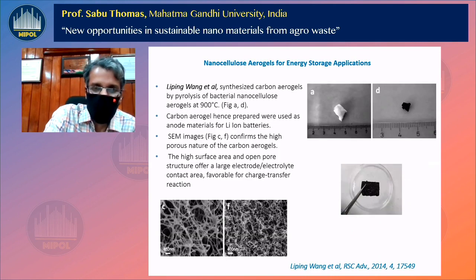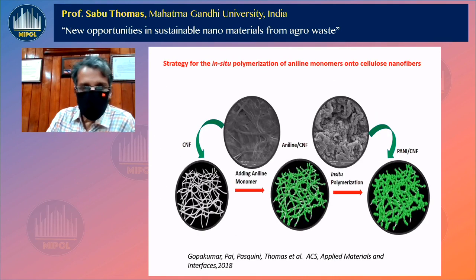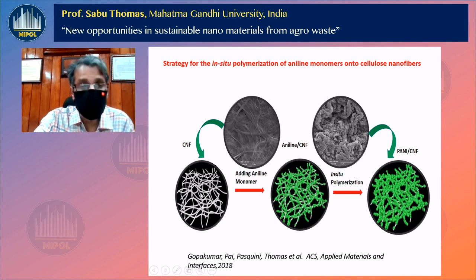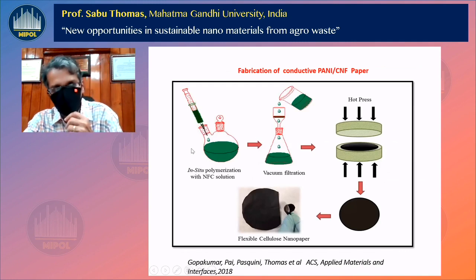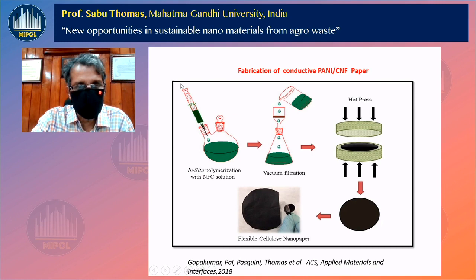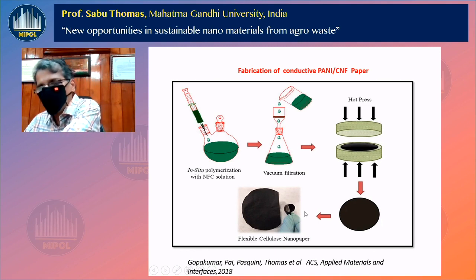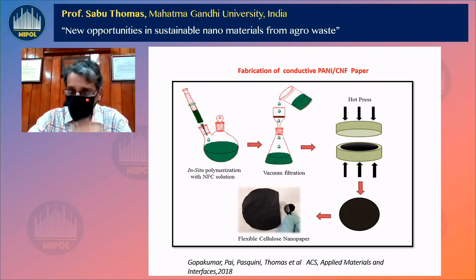I'm going to show you another interesting work. A PhD student of mine, Mr. Dibu, has made nanocellulose by hydrolysis. And then he mixed it with aniline, polymerized it, and made in situ polymerized polyaniline cellulose nanocomposites. Look at this, a very simple process. You can see the totality of the process. Nanocellulose dispersion, aniline is injected, you have in situ polymerization, vacuum filtration, and you get very flexible nanocellulose paper. It is extremely conductive.